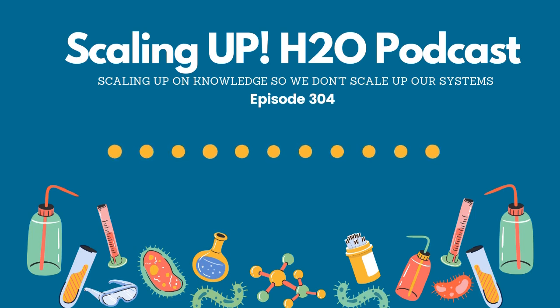And then we rinse those off, and then we put those coupons, now that we've got all the organics off of them, in an inhibited acid. What that inhibited acid is meant to do is to clean off all the corrosion byproducts from the exposure period that took place on that coupon. So now we've removed all the byproducts and we just have bare metal on those coupons. Now it's very specific in how we do that because we don't want to remove more metal than we have to. We just want to get the byproducts off. Once we get it to that stage, we then dry them.